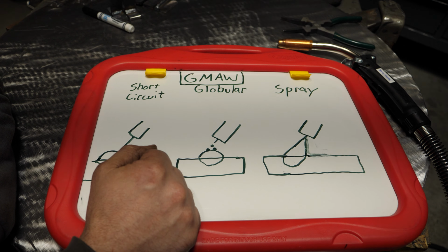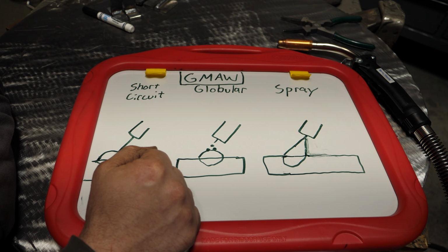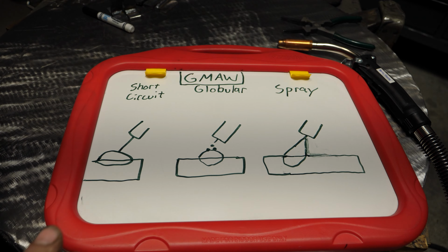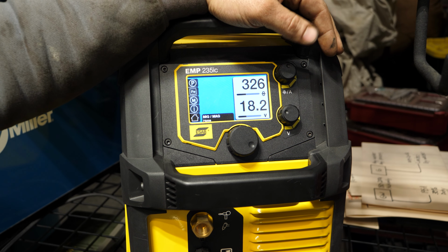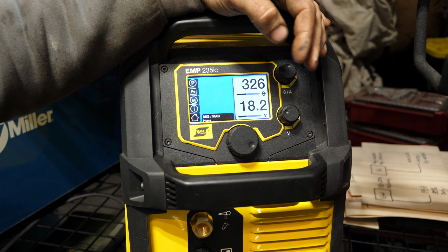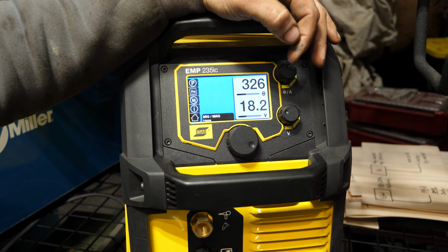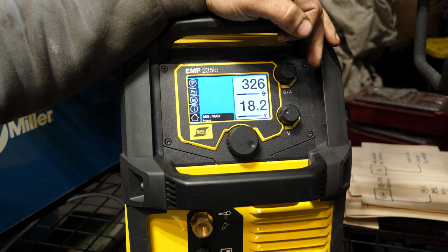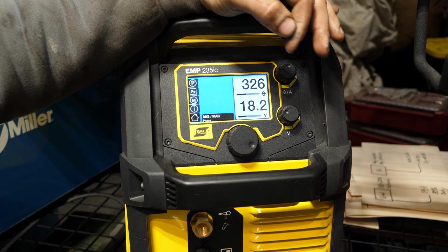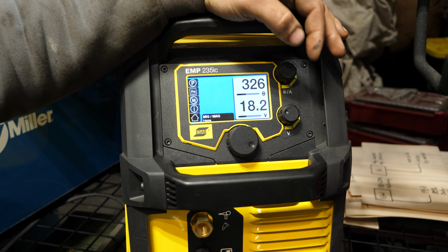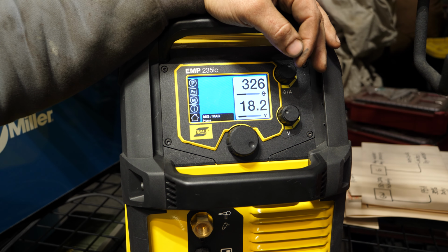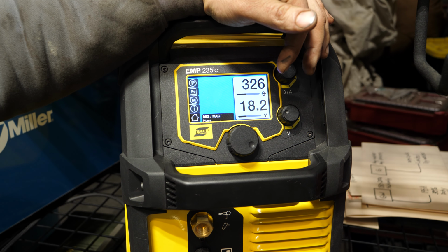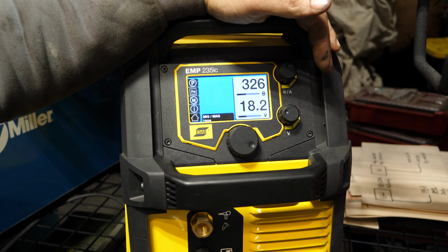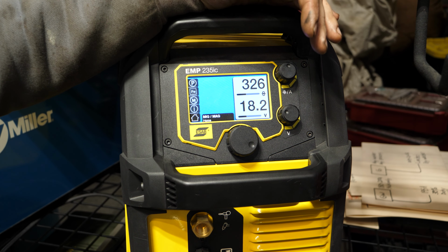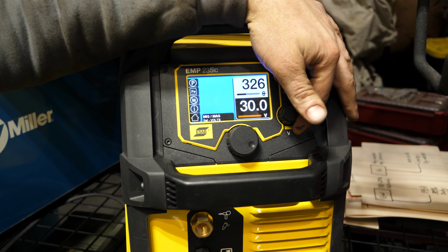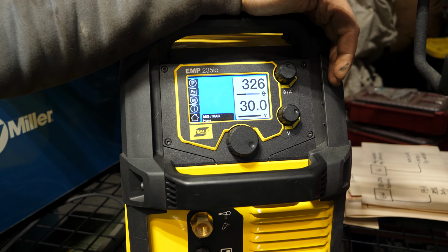Let's go and talk a little bit more about the gun setup, the welder setup, and then do some test welds. So the welder that you use matters, and today I'm going to be using the Rebel 235 by ESAB. This is an intermittent use 250 amp output welder, and it's more than capable of fully spray welding with .035 wire, which is what we're using today. Now, this has more than enough voltage potential to hit spray, and that's the big difference. This machine can actually hit 30 volts for a set point on output.